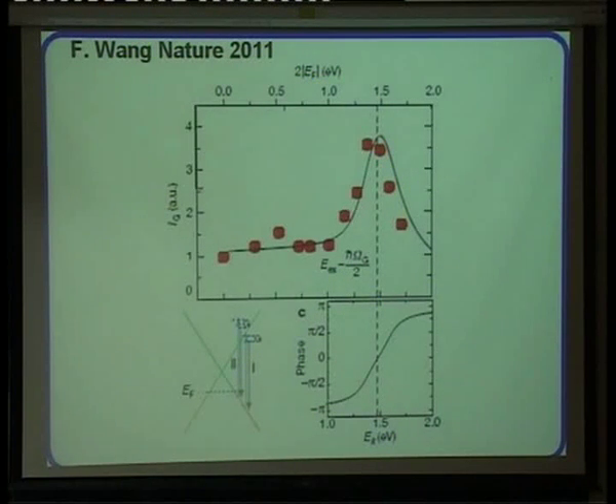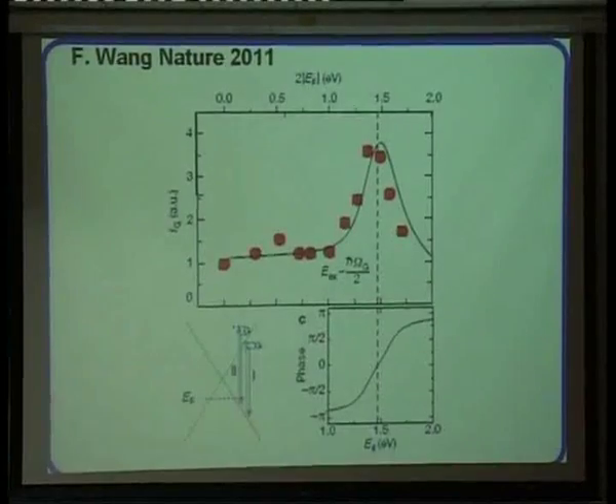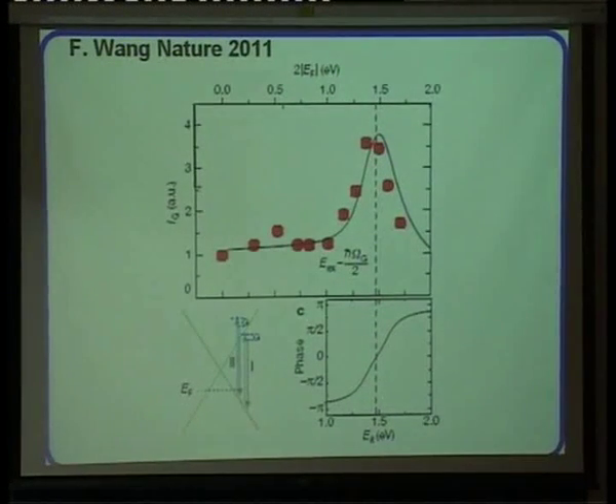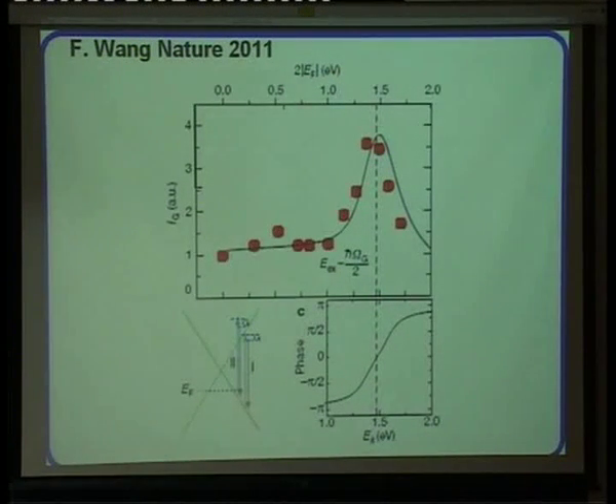So all the other terms that we throw away are actually important. The problem, experimentally, is that you need quite a lot of Fermi level shift, like 0.8. You need the laser energy divided by 2 to be of the same order of magnitude as the Fermi level, which means, since the lasers that people use in Raman are about 2 eV, you need about 1 eV doping, and doping a sample to 1 eV is not that simple. Actually, if you use a gate, it's impossible, so you need to do something else.